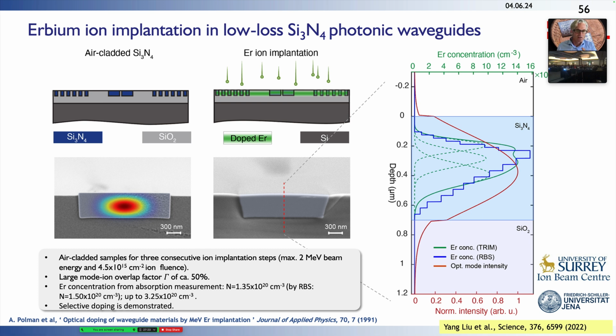And why is that? Because in this example, this was an 800 nanometer thick silicon nitride waveguide that had a loss before implant of about 3 dB per meter. What we have seen is that the implant at very high energies, high meaning here 2 MeV, 2 mega electron volt, starts to slightly deform the waveguides. The only reason the waveguide still has very low loss lies in the fact that it has a cladding on the right and left that provides physical protection during the implants. We have verified that after the implants, there's maybe a dB per meter more loss from the implant itself, but it still retains sufficiently low loss.